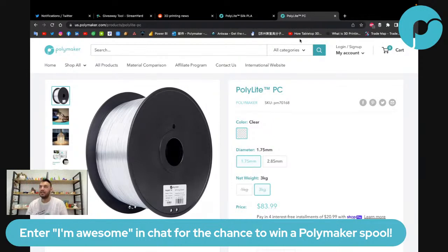Can you confirm the Polysilk if it performed better at higher or lower temp, and faster and slower speed for more shine? So theoretically, and also people had experience, the higher the extrusion temperature and the more shine you can get. But to a certain extent, because the higher the extrusion temperature, the higher risk you have to run into moisture issue. So if you print at 225, you will have a better shine than 205 or even 200.